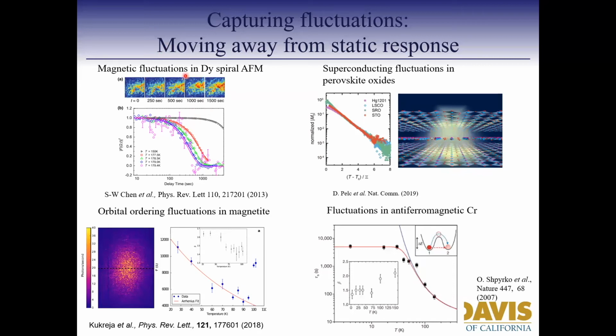So for example, magnetic fluctuations in dysprosium spiral have been seen almost 20 Kelvin before the transition in this material. Similarly, superconducting fluctuations have been observed in different superconducting systems. And even for orbital ordering and charge density waves in magnetite and chromium, people have seen that down to 10 Kelvin, or even at 30 or 40 Kelvin, these orderings actually fluctuate. They're not static as we think, and only change as we get to the phase transition temperature. For example, in magnetite, the metal to insulator transition temperature is around 120 Kelvin, and even way before then, you have these fluctuations which start to happen in these systems.